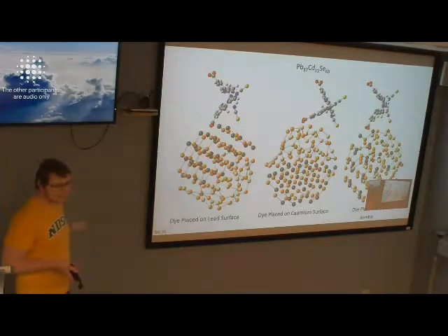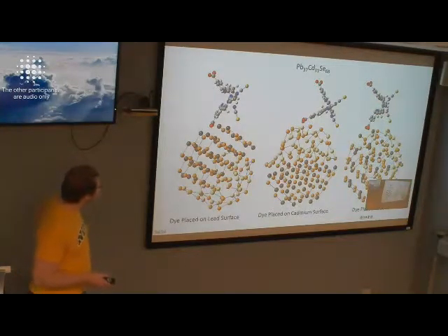You probably really need to start with both carboxylates already attached to the surface as the initial structure, and see whether it stays like that and whether the energy would be even lower. It looks like you already optimized it, so it probably stays that way, and compare with the total energy of these structures.